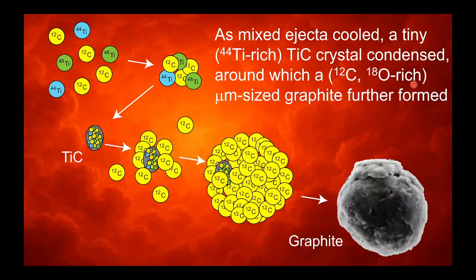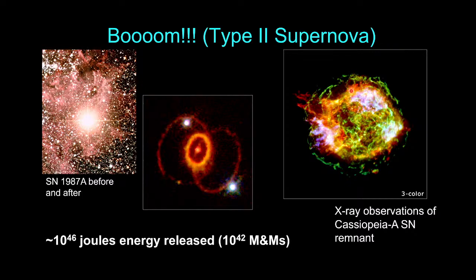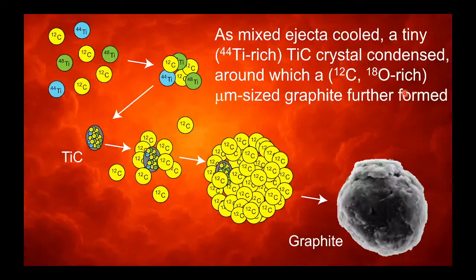So now we imagine this ejecta going out into space. At some point, in this phase or this phase, some of the gas is cooling and eventually reaches the stage where the atoms can stick together and condense into dust. And so what happened in this carbon-rich layer of the star is, first at high temperatures, you had titanium and carbon forming a little grain of titanium carbide, a rare mineral. And some of that titanium was titanium-44 from the center of the star. And that titanium carbide, as it cooled, then started collecting carbon atoms, like I showed in that image earlier on, and eventually formed this ball of carbon. So it's mostly graphite, but it has this titanium carbide crystal.